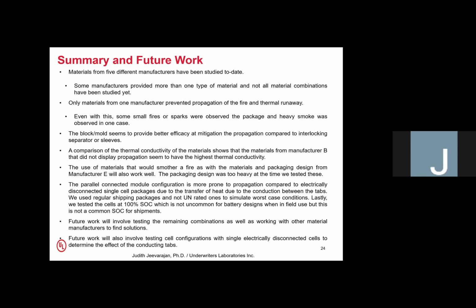And the block mold seems to have a better efficacy. Even from our previous tests, we did find that that design works better than just having interlocking separators or sleeves. And as I mentioned, the thermal conductivity of the materials shows that that is pretty important in preventing the propagation. And also wanted to reiterate that we are looking at worst case conditions for all the variables we've used in our protocols. So just wanted you to keep that in mind.